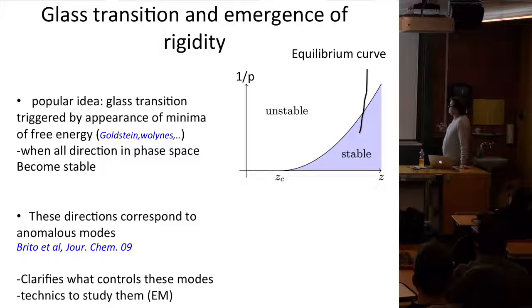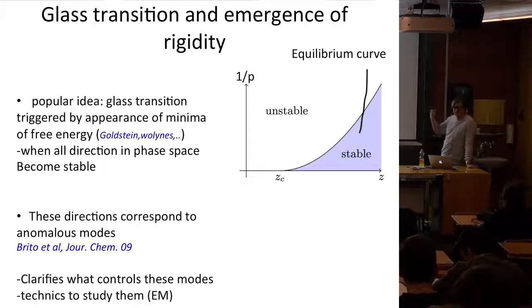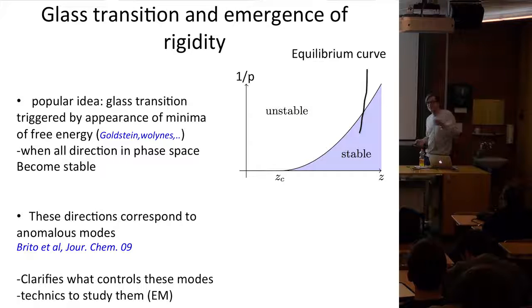All right. So now let me just briefly mention how this... And then I will come back as to why it's like that. But first, let me also comment on another idea which I think is interesting. It has to do with the glass transition. How do you enter this glass phase? There has been a popular idea, I think initially proposed by Goldstein, but also very popular for mean field approaches to glasses, that the glass transition has to do with a transition between a high temperature or low packing fraction regime where the free energy you live close to saddles, you always have unstable directions in phase space, and then at low enough temperature, or here in this context at large enough packing fraction, you suddenly have states that are metastable, and the dynamics becomes activated.